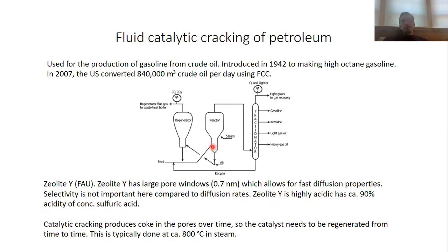So you actually get a mixture of these cracked hydrocarbons, and then you can separate them by fractional distillation into heavy gas oil, light gas oil, kerosene, gasoline, and lighter gases. That zeolite that performs this acid catalysis does not have infinite lifetime. Over time, there's coke formation within the zeolite pores that eventually will block the pores and degrade the catalyst.